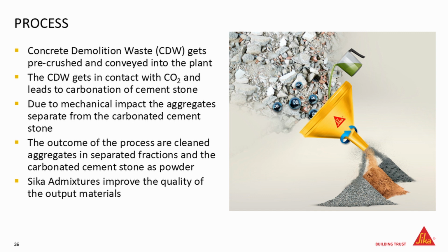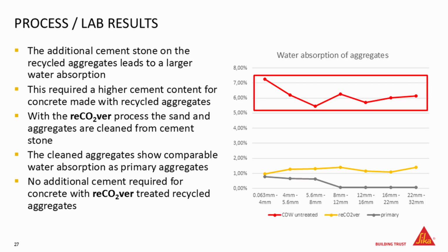So at the end of the process, we have the aggregates, we have the sand fractions, and we have the separated cementitious parts in a powder. And that is basically the outcome of that. And again, why do we do that? This is because we want to reduce the water absorption of these aggregates. And by reducing the water absorption, by cleaning them, we can open this field much more, so that everybody can use recycled aggregates to produce concrete with a lower CO2 footprint.